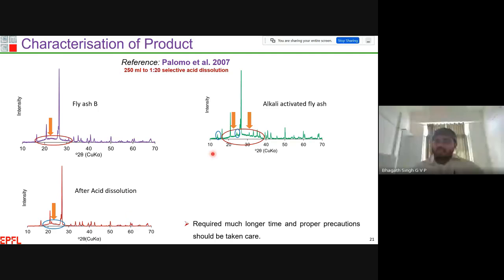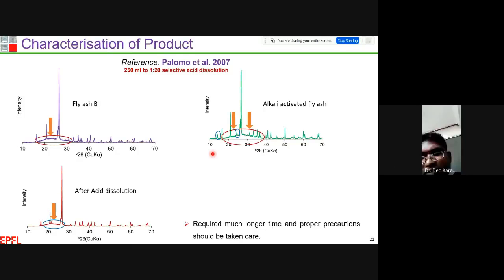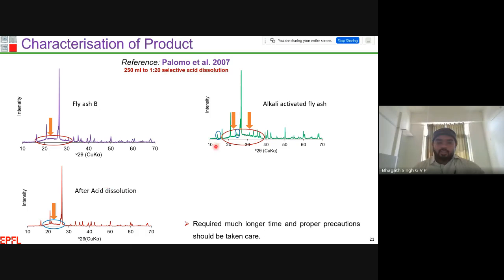Then the drawback of this methodology is that it requires much longer time, and also we have to take proper precautions while we analyze the reaction product as well as how much glass is left over in the system with respect to time. And we have to wait at least 3 to 6 hours to get the results of how much glass has reacted, how much reaction product is formed during this activation process.